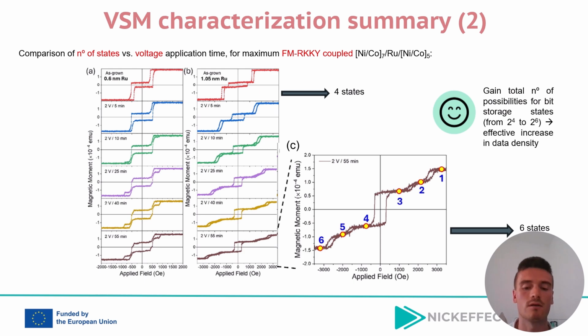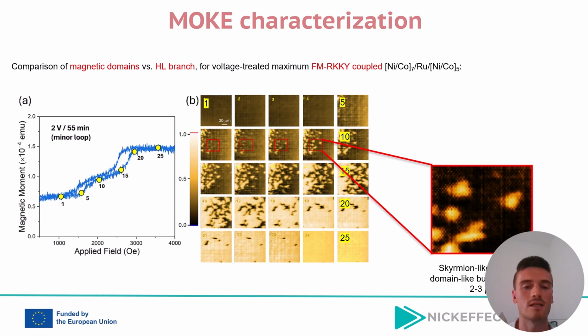potential high-density memory applications. Next, magneto-optical Kerr effect characterization of a voltage-treated ferromagnetically RKKY coupled sample, precisely this 1.05 nanometer ruthenium thickness one mentioned and studied in the slide right ahead, was attributed to some Skyrmion-like bubble domains